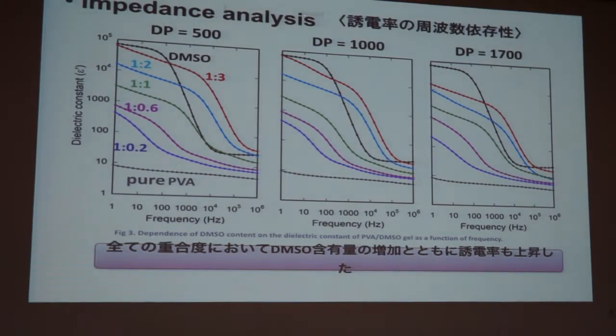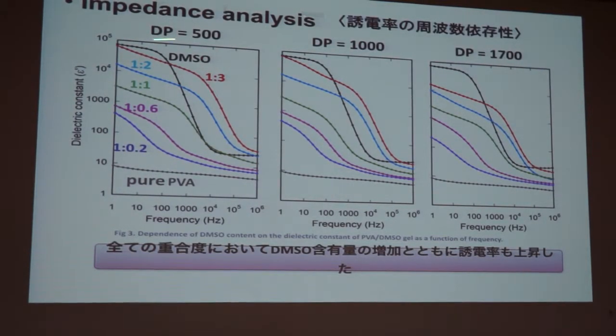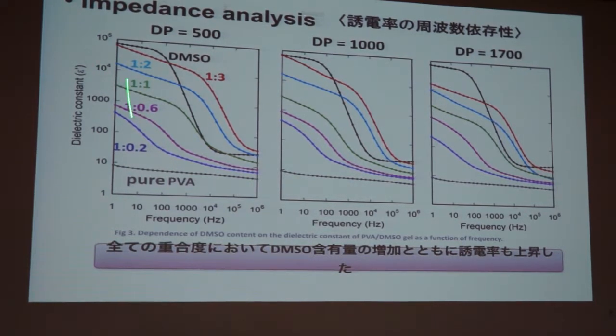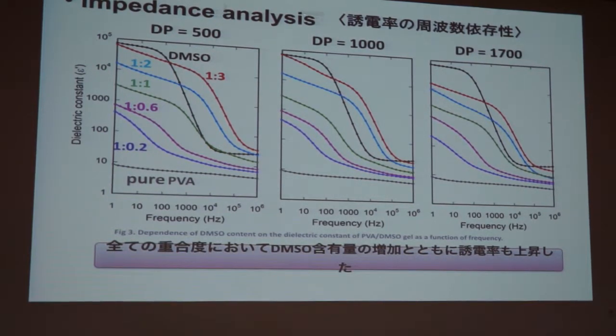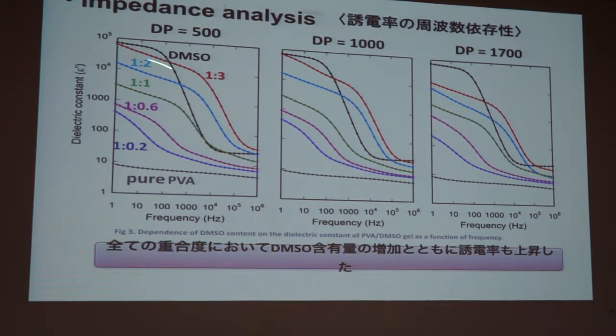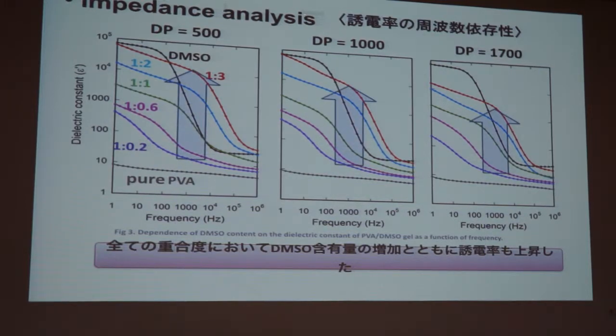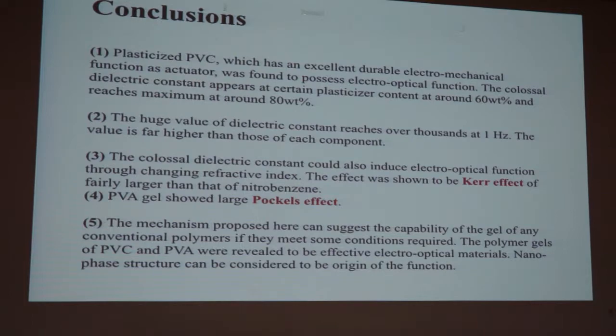And in the other case, dimethyl sulfoxide can be used as a solvent. In the very low frequency range, we can use a very large dielectric constant, around 1,000, very high. So in this sense, we can use DMSO gel also. But so far, it doesn't work well. Impurity is a large amount. It's not complete for practical use.